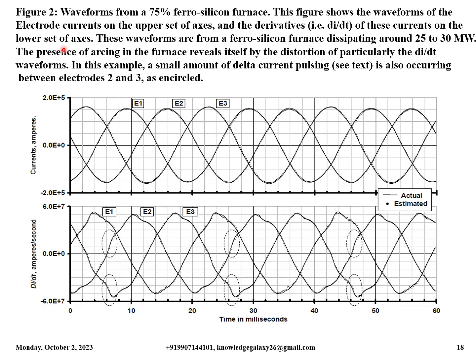So this is figure 2, which shows waveforms from a 75% ferrosilicon furnace. This figure shows the waveforms of the electrode currents on the upper set of axes and the derivatives, that is di by dt, of these currents on the lower set of axes. These waveforms are from a ferrosilicon furnace dissipating around 25 to 30 megawatt.